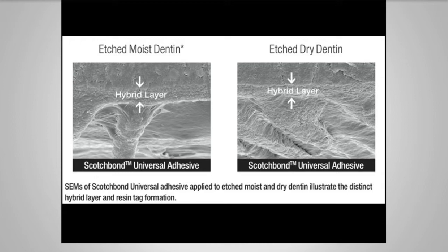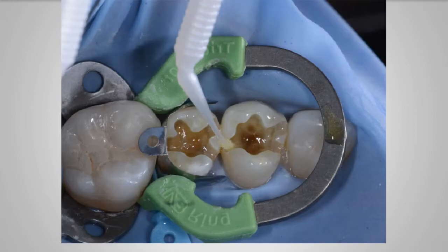I'm really enjoying using this product, and I think you'll find that the research out there supports using these newer adhesives with at minimum selective etching of the enamel margin. The research still shows that we're not getting as good a bond on enamel as we could by etching it. So doing two steps and etching that enamel at least is helpful. To keep it simple, I just etch everything, because some of the other data shows that we can get a little bit of increase in strength by etching that dentin. Not much, but enough.